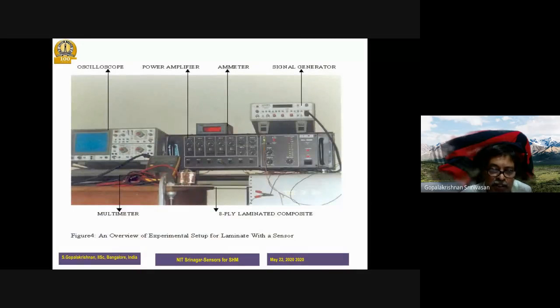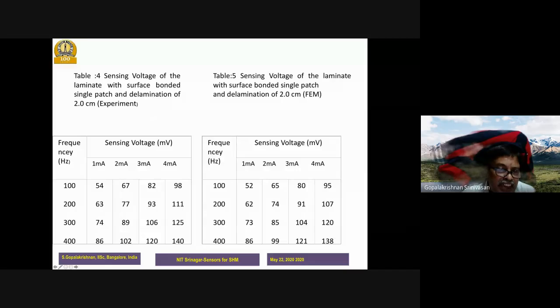And this is the experimental system. You have a signal generator, the ammeter to measure the current, a power amplifier to amplify the voltage, and the oscilloscope to see the responses. And this is the experiment, and this is the theory. When we trigger the signal, the signal is an AC sine current, I equals I naught sine omega t, where omega varies from 100 to 400 hertz, and I naught varies from 1 milliampere to 4 milliamperes. And we were able to measure the voltage, and we were getting very good agreement between my numerical finite element model and the experiments.